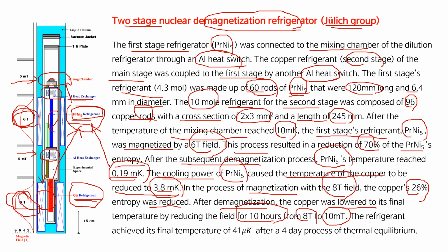Then the refrigerant achieved its final temperature of 41 microkelvin after a 4-day process of thermal equilibrium.